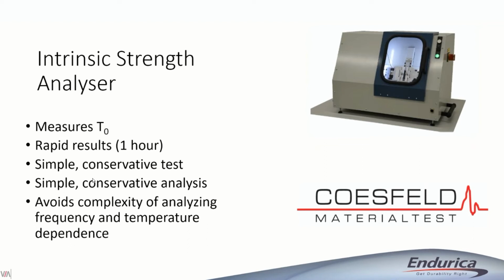If you've ever tried fatigue measurements at those types of frequencies, you start to worry a lot about how much stroke you can get and how much power you have to feed into the machine. And what we ended up doing for that customer was using this intrinsic strength measurement. We just said, hey, look, it's really hard to measure at that high frequency. Maybe we could just make sure that we're below the fatigue limit, and that way you've got infinite life, and you can stop worrying about frequency and temperature. So that was an approach that worked in that particular case.